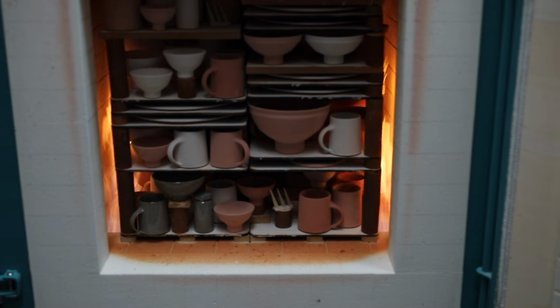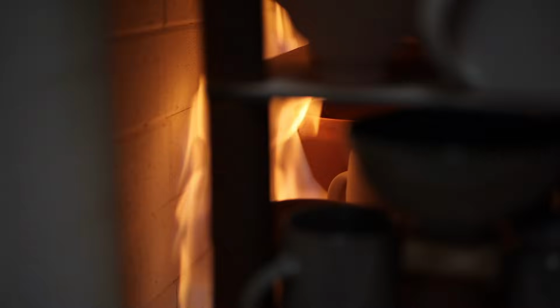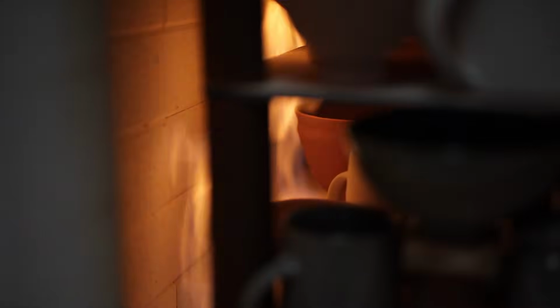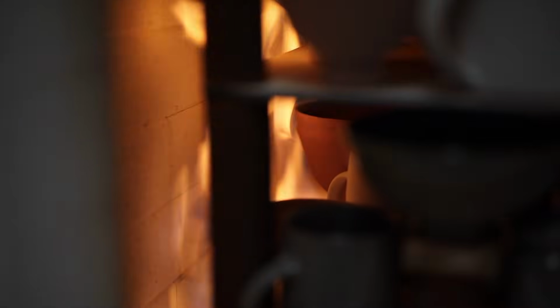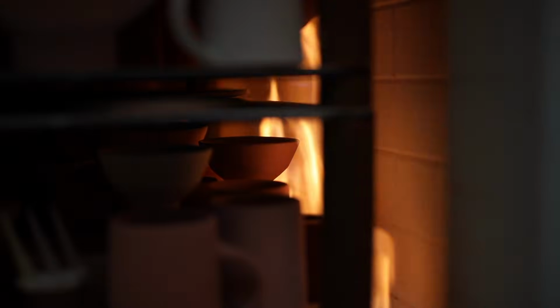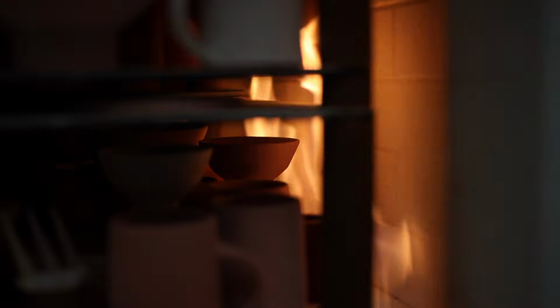And initially the gas pressure is kept really low. This way the temperature rises slowly initially. If you fire pots too quickly, they will explode, as even at this point they can contain moisture, and if that all suddenly turns to steam, the pots will quite literally explode.